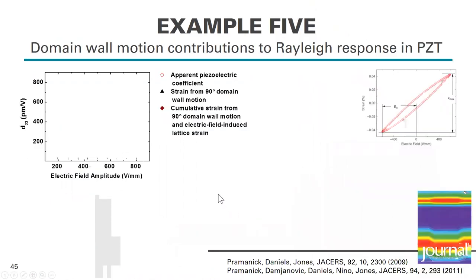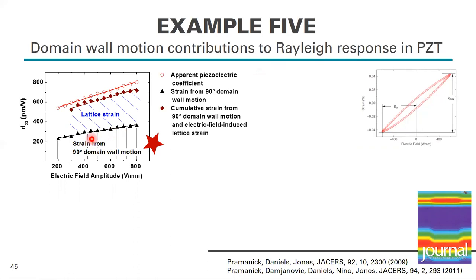Example five is the work of one of my first PhD students, Abhijit Pramanik. So we decided that based upon the work on the previous slide, we should expand this a little further into other compositions, and in particular, study the Rayleigh behavior. So the change in the piezoelectric coefficient as a function of field amplitude. And so we took piezoelectric coefficient data in collaboration with Dragan Damjanovic, and then we did these X-ray experiments, and we calculated the contribution from 90 degree domain wall motion to that macroscopic piezoelectric coefficient.